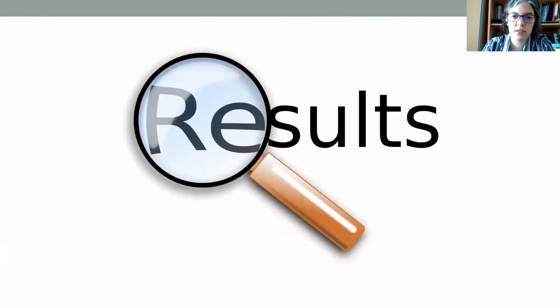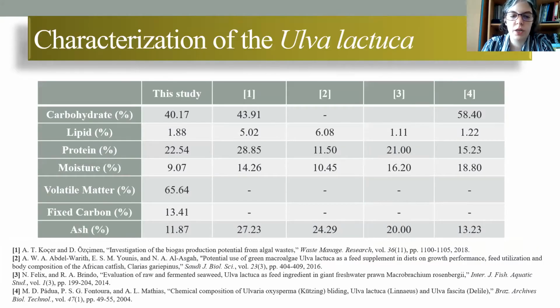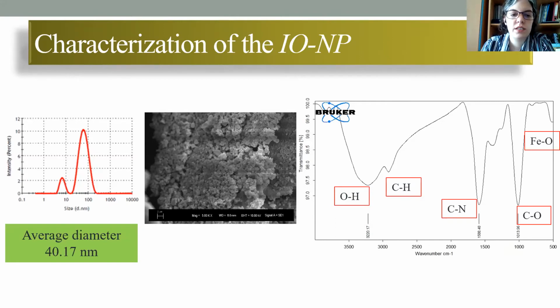So let's see the results. Firstly, we characterized our raw material, Ulva lactuca. Its chemical content is a little different in comparison with the literature, but this is expected due to seasonal changes and the location site. After that, we characterized the iron oxide nanoparticles. Our nanoparticles have very small sizes. The average diameter was 40 nanometers, and as you can see in the figure, there are two peaks. This shows there is agglomeration, and in the same image you can see the nanoparticles are spherical and in an agglomerated state. Also, with FTIR, we see the iron oxide peaks in the spectrum.